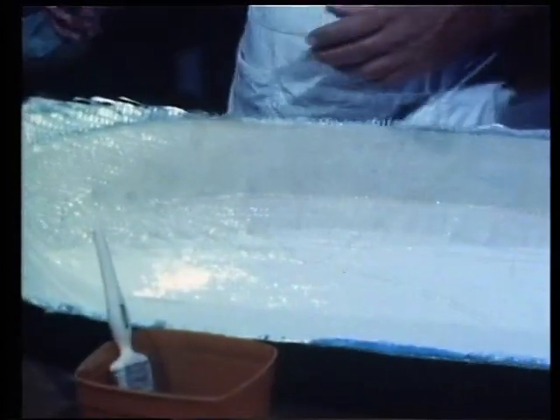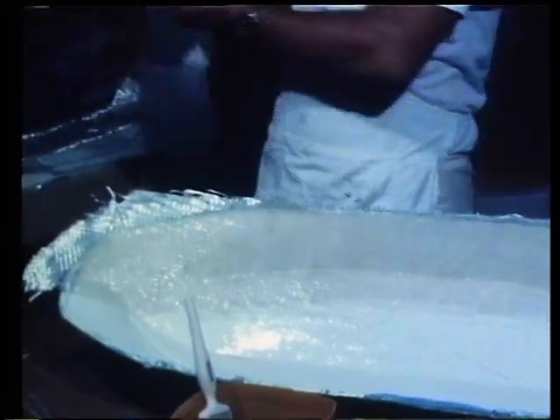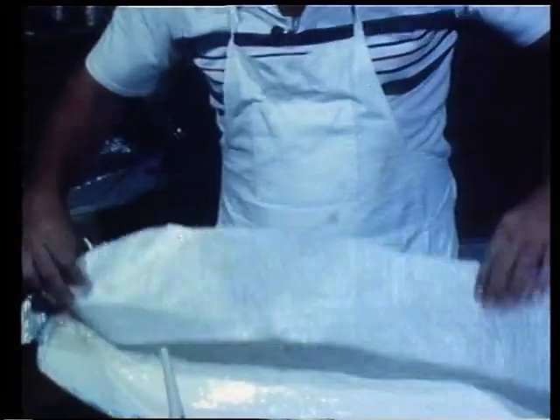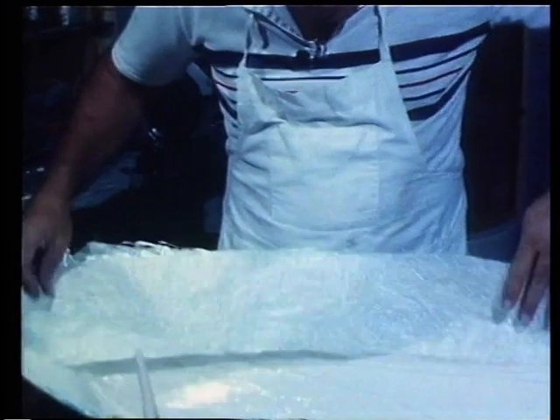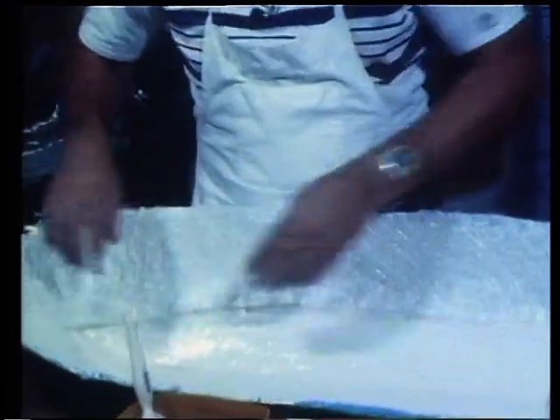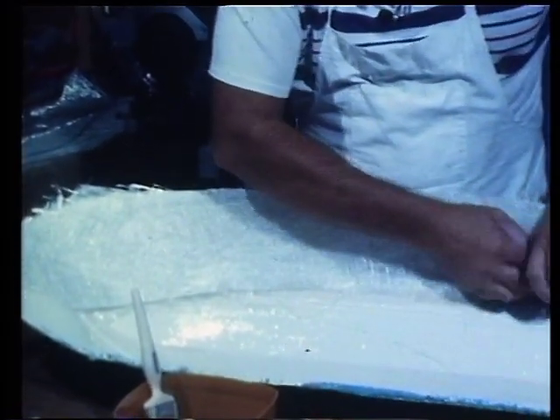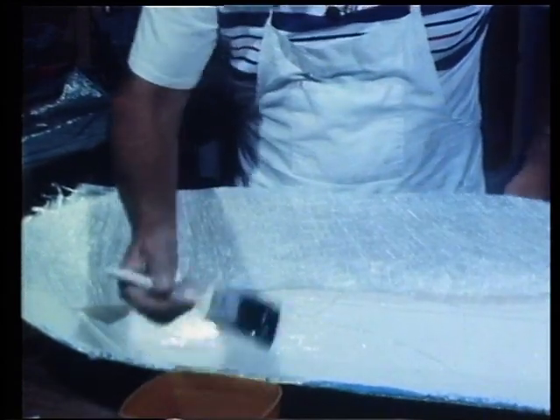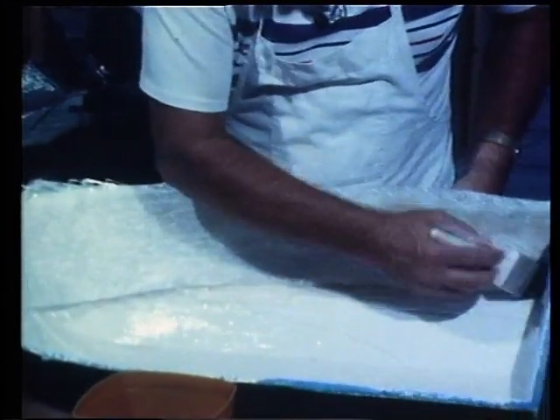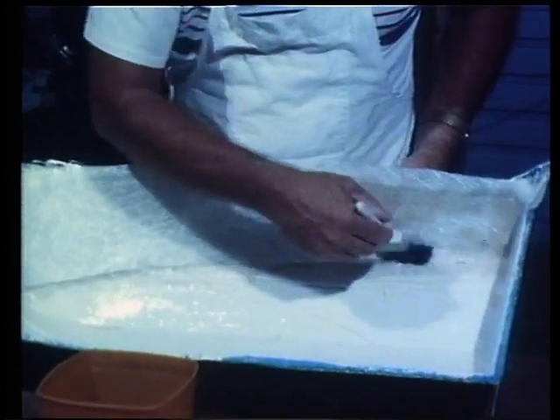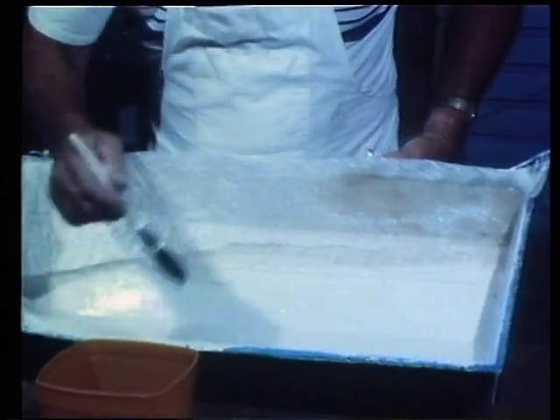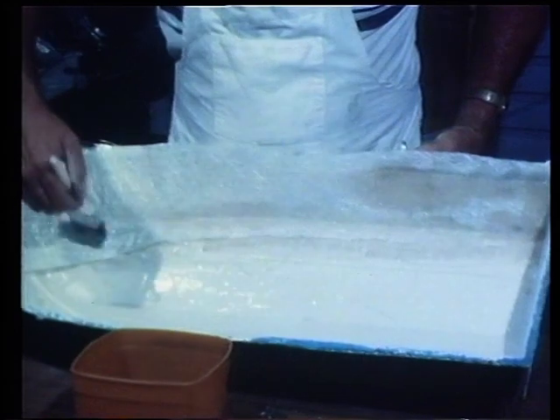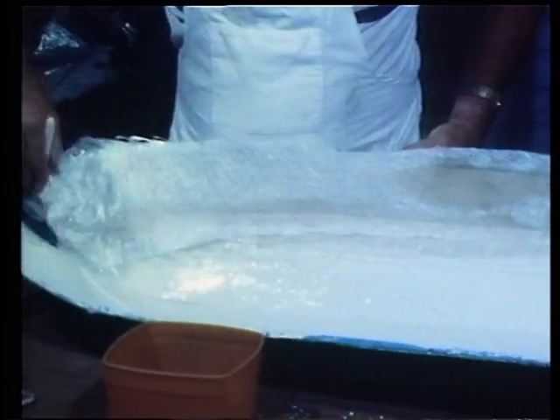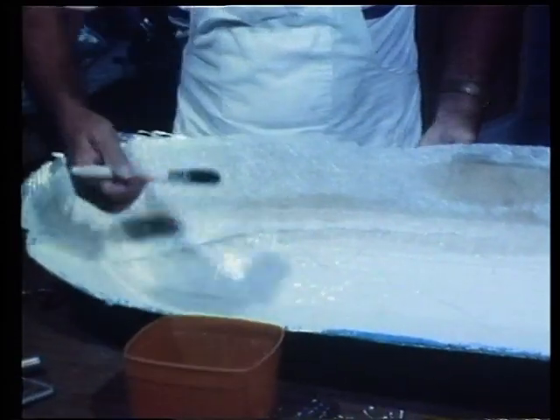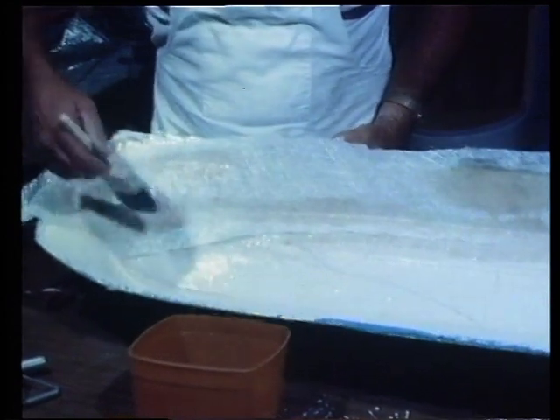Now, once your woven roving is in, it's time to put another layer of mat over the top. As you go through the laminating process, it becomes easier and easier to wet it out because obviously you have resin underneath that you can work up through. In fact, that really is the secret of fiberglass laminating, the fact that rather than trying to put the resin down through the mat from the outside, or the roving for that matter, it's far better to work it up from underneath and supplement the wet out by applying resin to the outside surface.